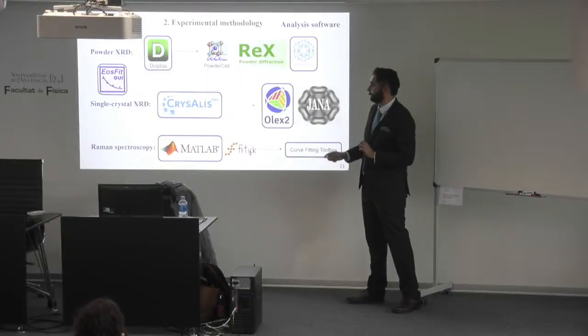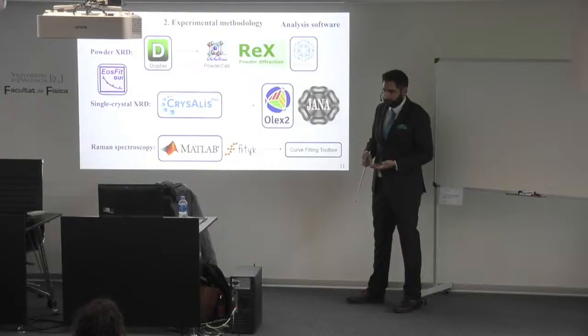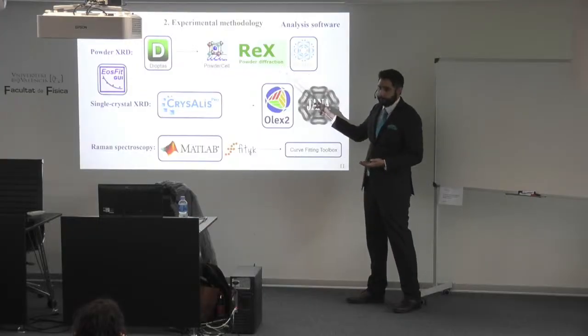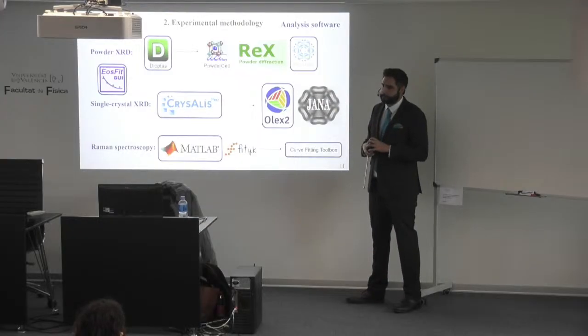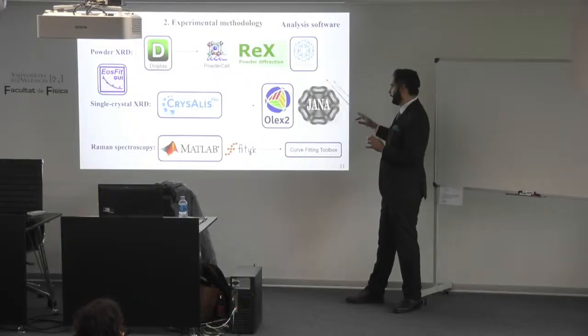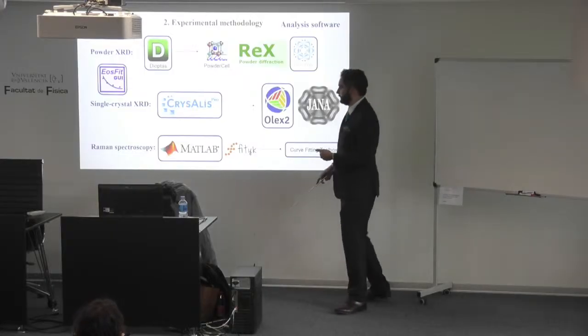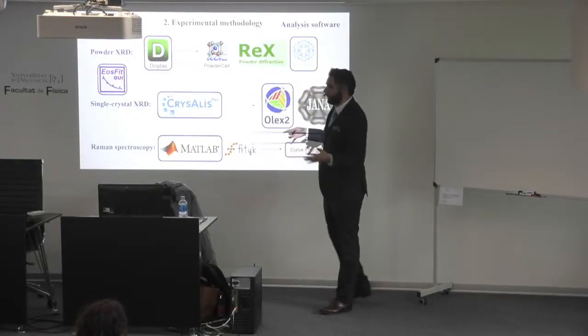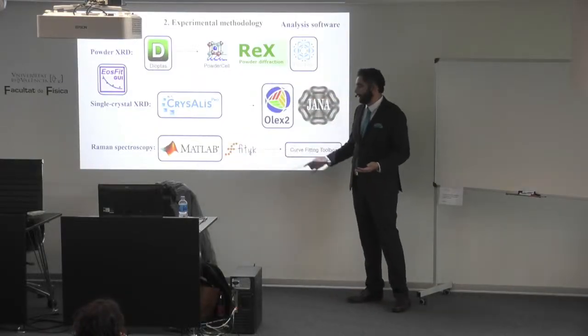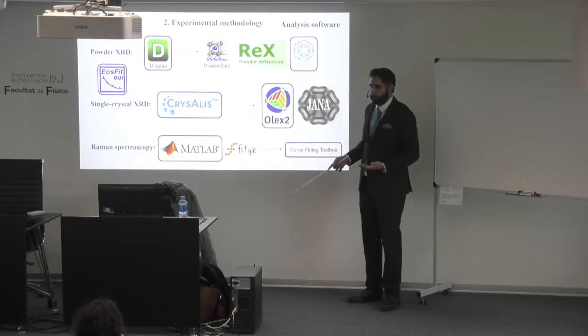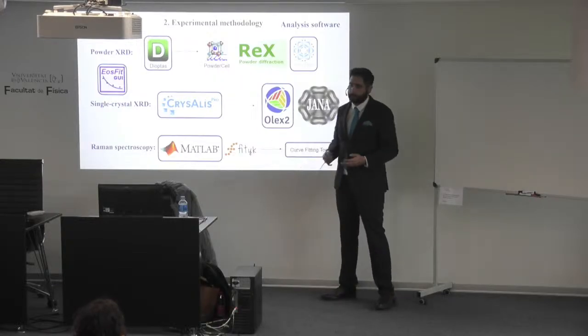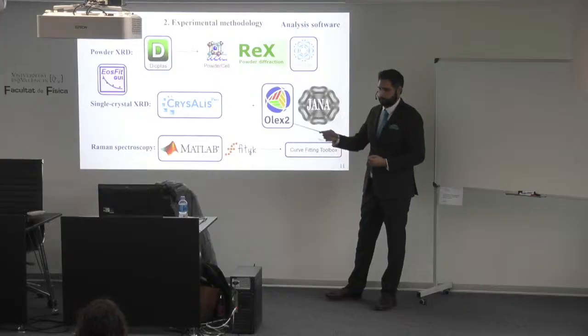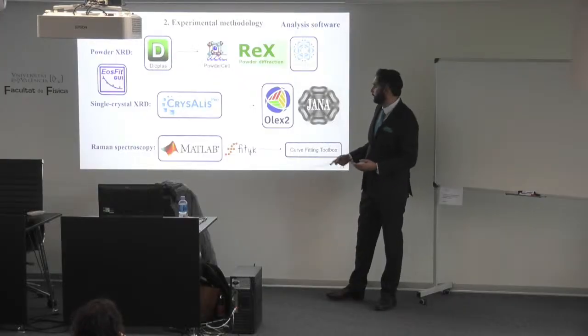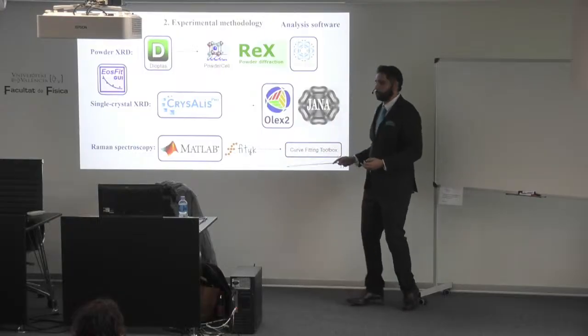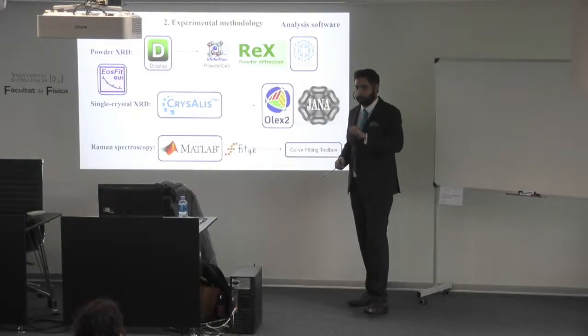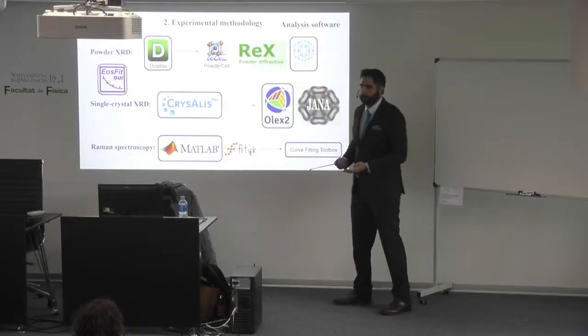This is different from the powder, because we can find atomic positions with Rietveld analysis with powder, but at high pressures the diamond anvil cell is going to condition this. So in this case, single crystal has a little advantage. And for Raman spectroscopy, the free software that I've seen the most is Fityk, but in our case, we had access to MATLAB and some functions that, for example, Julio gave me that are really useful, so I took advantage of this. And then when we try to find the pressure coefficient of the modes, we just use some fitting tool in order to get it.